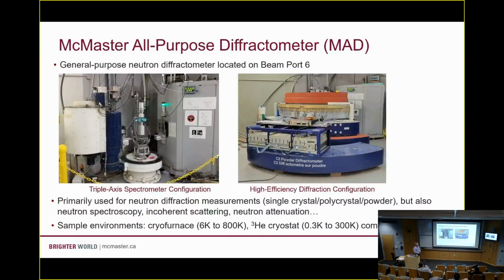Okay. So just quickly to show you what the instruments look like at the moment, this is our all-purpose diffractometer. This is sort of our workhorse instrument at the moment. It does a little bit of everything, single crystal, powder diffraction, spectroscopy, although pretty slowly, incoherent scattering to look at hydrogen materials, attenuation. It has a triple axis configuration here. More recently, it's been operating in this high efficiency diffraction mode using this 80-degree detector that we inherited from Chalk River. And we're sort of building up our stock of sample environments to look at structural and magnetic changes over a broad range of temperatures.